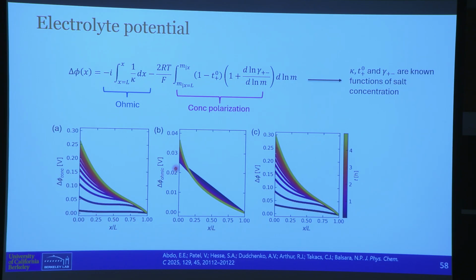And you can see that the ohmic term is 0.04 volts. This is 0.25 volts. It's completely dominated by transference and activity coefficients. You might as well not measure the conductivity. Okay? I would say improving conductivity, at least relative to PEO, is pointless. You will not affect the voltage at high currents. You need to do something about the transference, which is what PPM allows you to do.